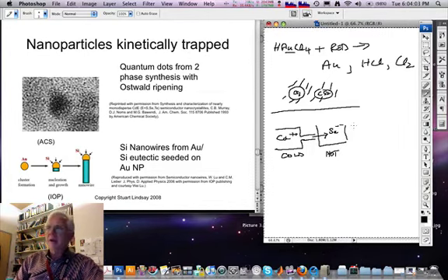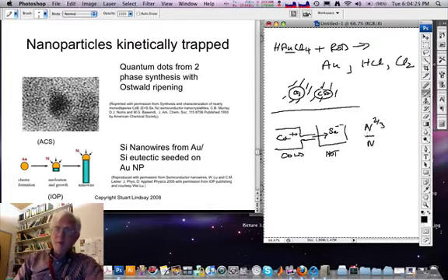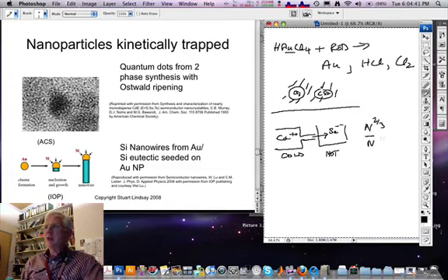A second step, interestingly enough, is then to cycle the temperature of this suspension from a low temperature to a high temperature and back again. It turns out that because of the importance of surface effects, so that the free energy per particle, if you remember, was like n to the 2/3 over n, the smaller particles have more driving free energy for incorporating extra atoms, and so thermal cycling, the small particles grow at the expense of the larger particles, and this tends to produce a more monodispersed population of nanoparticles. This process is called Ostwald ripening.